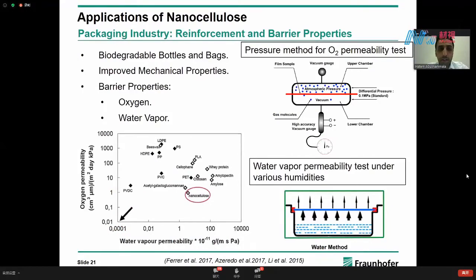Nanocellulose is very interesting also for the packaging industry, because if you want to design biodegradable bottles and bags, nanocellulose is interesting. It improves the mechanical properties, and mainly it improves the barrier properties. We are talking about oxygen and water vapor improvement. As you can see in the figure below, nanocellulose has a very low oxygen permeability with a pretty decent water vapor permeability.